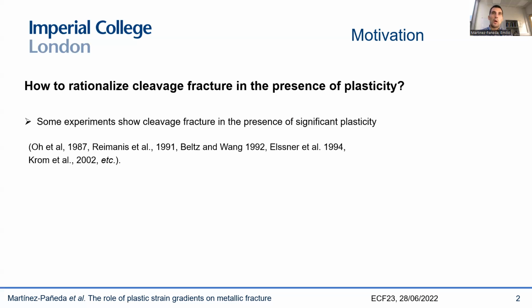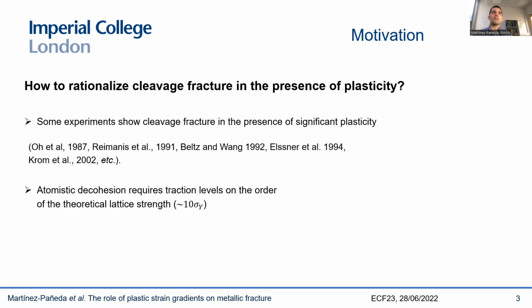And this has always been quite puzzling for us, because we know that atomic decohesion requires attractive stresses on the order of the atomic or the theoretical lattice strength, which is 10 times the yield stress. Even if we think of a grain boundary, we know that we need stress on the order of 9 times the yield stress to effectively decohere a grain boundary. So this is puzzling to us because in the context of conventional continuum theories, there's no way that we can achieve those high levels of stress that are needed to reach these cleavage fractures that we see in those experiments.